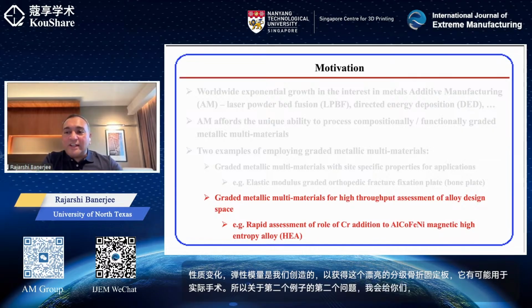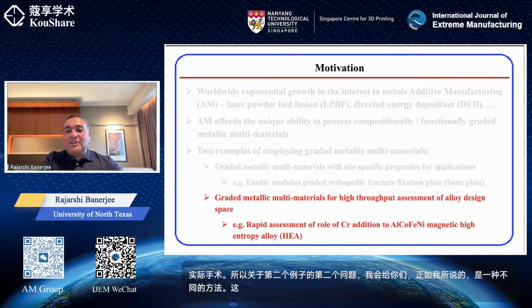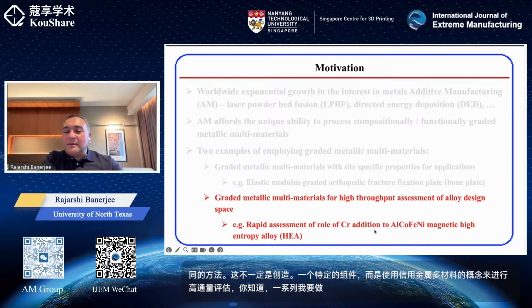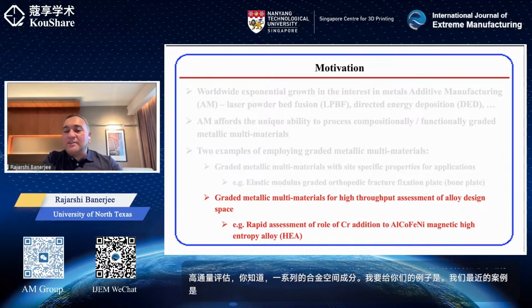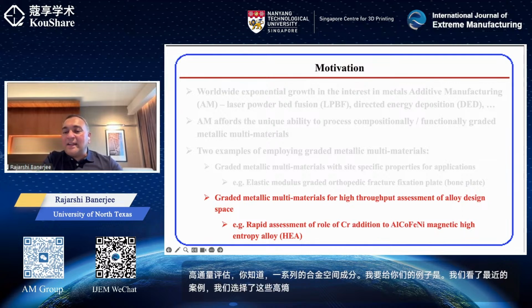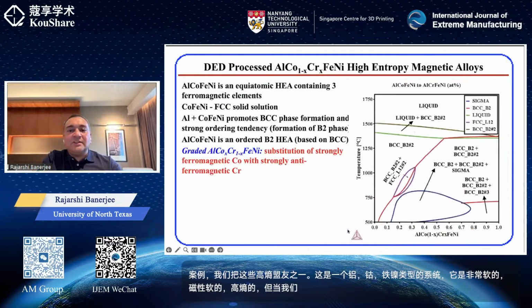This is not necessarily to create a particular component, but to use the concept of graded metallic multimaterials for high throughput assessment of a range of alloy space compositionally. The example I'm going to give you is a recent case where we take one of these high entropy alloys, an aluminum, cobalt, iron, nickel type system, which is a very soft, magnetically soft high entropy alloy, but then we add chromium to it. And the rationale behind that I will explain in the next slide.